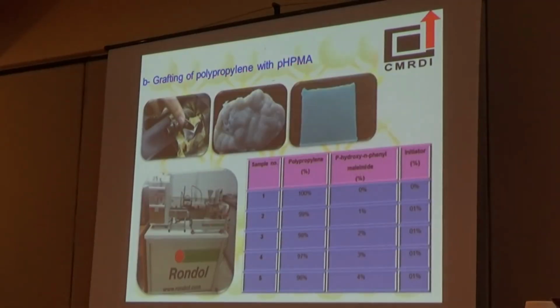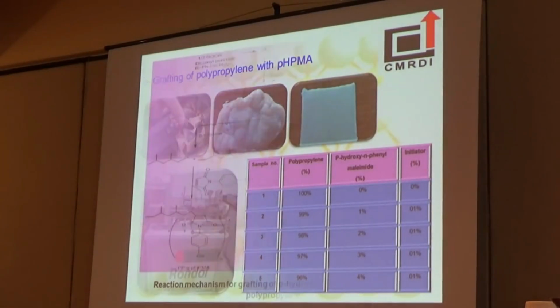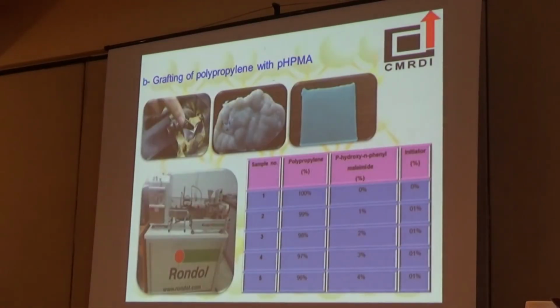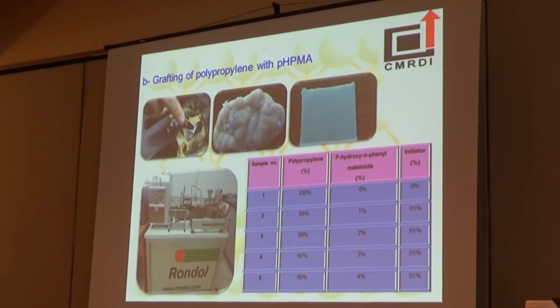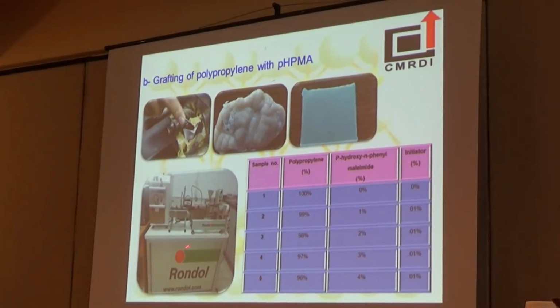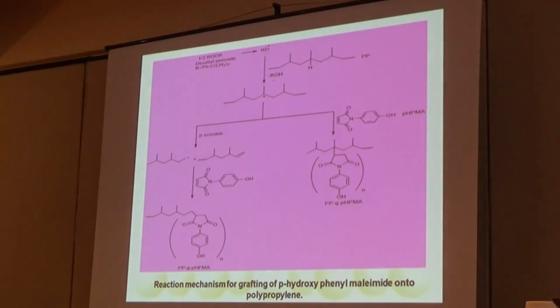Then, polypropylene was grafted with different weight percents of the prepared monomer in the presence of a fixed initiator percent using the melt mixing method in a twin screw extruder. The proposed reaction mechanism of the grafting reaction is as seen here.